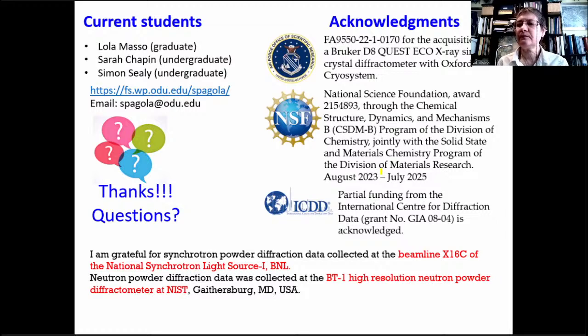Thank you. A wide range of solvents was used for many of the experiments, such as the synthesis of TTF-CAH2. The solvents were grouped according to their polarity, but there was a large difference in viscosity as well. For example, DMSO, high, hexane, low. Do you know of any consistent effect of the solvent viscosity on polymorph formation?